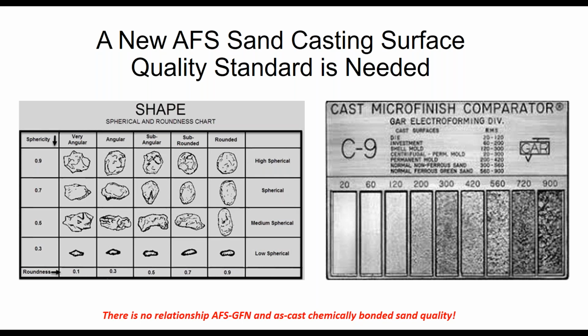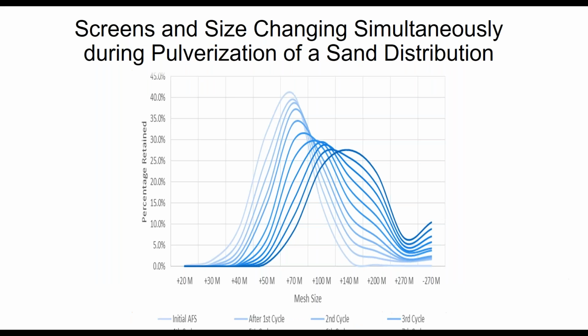Certainly, if we look at the grain fineness number as defined by AFS and the as-cast chemically bonded sand quality that we get, when we put a binder on that sand and it meets molten metal at the mold metal interface, that's where the magic happens. And that particular magic is due to thermomechanical, thermochemical, thermophysical properties. And I want to talk to you certainly about how do we get to qualify that? How do we performance predict what will happen there? But before I go there, I have to talk a little bit more about the durability of these sands.